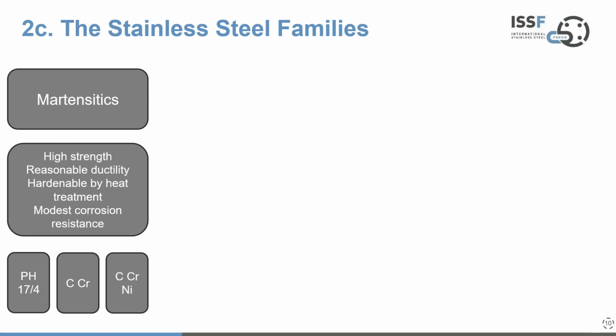So let's now look at the stainless steel families. And I'll start with what are known as the martensitic group. And one of the grades in here is very similar to that Harry Brearley created back in 1913. But this group of stainless products are really described as having high strength, reasonable ductility, but not excellent. They are hardenable by heat treatment, and they have, we would say in our world, modest corrosion resistance. That's still somewhat better than carbon steel corrosion resistance, but in the world of stainless, it's at the lower end of our spectrum. And broadly, we've got 3 families there: precipitation hardening grades, carbon chromium grades, and then carbon chromium nickel grades.